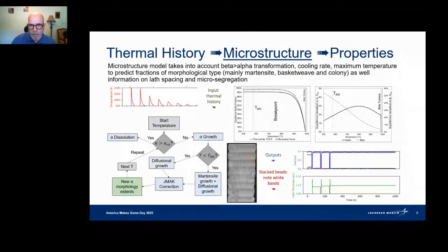And one of the really relevant discoveries that Tony and his group made, it's difficult to see in this particular stacked bead, but if you look closely, there are these white bands that are evident across this sample. And initially, I certainly defaulted to thinking those white bands were relevant or tied to the bead geometry, each layer as we went up. That's not true, though. The bead layers can be seen in the geometry of the part itself. So these white bands were actually a byproduct of the thermal history. And it had to do with the amount of reheating and how close we were to the transus temperature. Tony can give you a much better explanation of that if you're interested in hearing that.